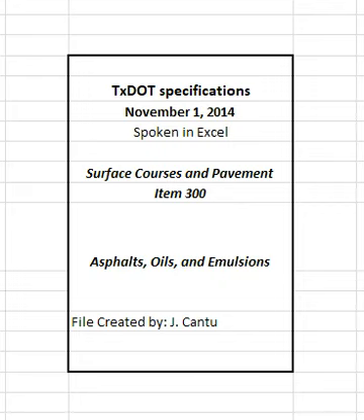2. This requirement may be waived at the department's discretion if the supplier warrants that the asphalt binder can be adequately pumped, mixed, and compacted at temperatures that meet all applicable safety, environmental, and constructability requirements. At test temperatures where the binder is a Newtonian fluid, any suitable standard means of viscosity measurement may be used, including capillary, T201 or T202, or rotational viscometry, T316.